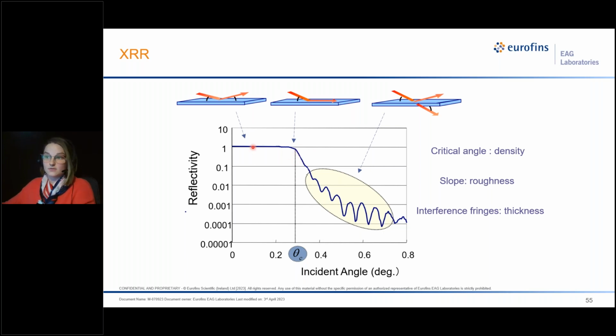And where this drop is, so if it's over here versus over here, is going to determine the density of your film. The next thing we think about is after the fact, we're going to have some x-rays that go into the sample and then reflect from subsequent layers and some that are reflecting from the top. And the constructive and destructive interference is what's going to give you these interference fringes. So the slope, if we have a very shallow slope, that's a very smooth sample. If the fringes drop off very quickly, you have a very rough sample. And then the frequency of your fringes gives you the thickness of your film. So if you have several large fringes, you have a very thin sample. If you have lots and lots of fringes, so very high frequency of fringes, you have a very thick sample.